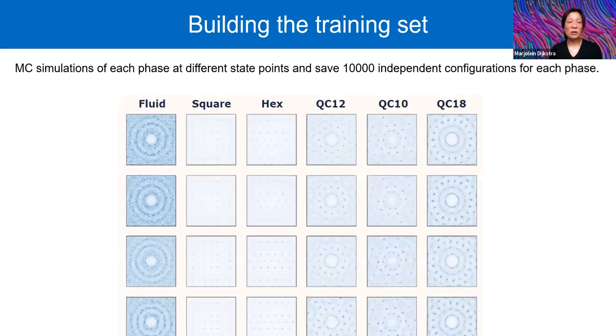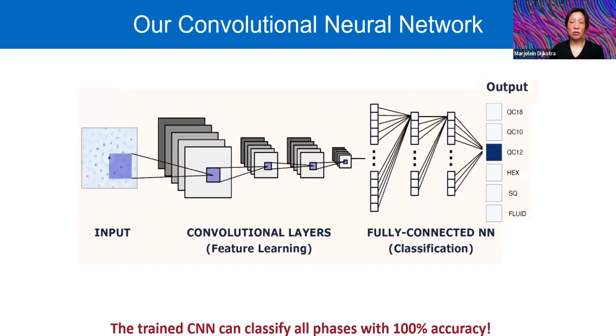And so we first performed Monte Carlo simulation for all the phases that are present in the system: a fluid, a square, a hexagonal, and the three different quasicrystals. We then save 10,000 independent configurations. We calculate the diffraction patterns, and we then train a convolutional neural network to recognize the different phases according to their diffraction patterns. And so we have six output nodes that tell us what the probability is that it belongs to one of these phases. And this probability is very nice because you can immediately use it as a fitness function.